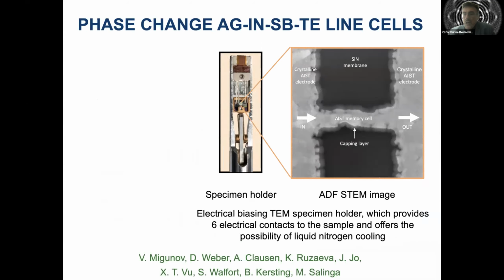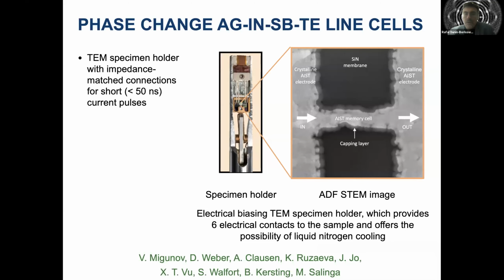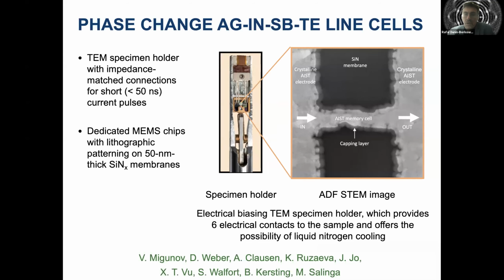So in this case, on the right-hand side here is an annular dark field STEM image of an individual memory cell. This is only 300 nanometers long and about 80 nanometers wide. And the challenge here is that we have to pass nanosecond pulses through the device. And this means that the specimen holder has to have impedance matched electrical connections. We have to have dedicated MEMS chips where the device works outside the TEM and inside the TEM. And we have to have additional layers to stop the device evaporating because there is no large heat sink underneath the device inside the TEM.